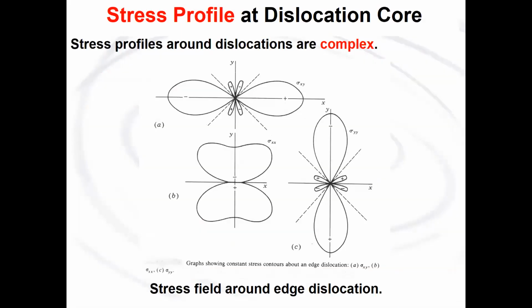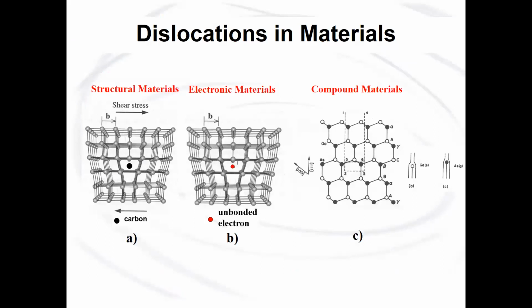Dislocations have a very complex strain field around themselves, and this is because of the atomic planes. These haven't been able to be studied in detail because we actually haven't been able to measure the strain field around these. We see that the dislocations in structural materials, at the core of the dislocation, there can be an impurity such as carbon in iron, which forms steel, and it produces Cottrell locking. In electronic materials like silicon, you can have a dangling electron, so the dislocation forms a charge at the core, and is essentially a wire, which when it drifts into the active region of a device can drain the charge and the device fails. In photonic materials such as gallium arsenide, you can have various types of dislocations.